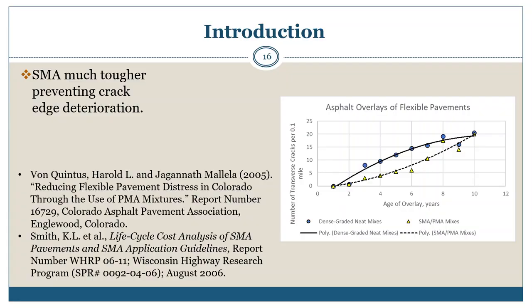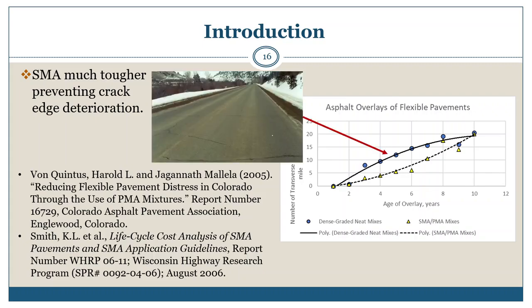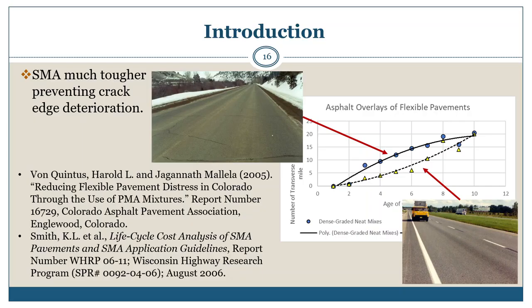The observations on crack deterioration were taken from a study in both Colorado and Wisconsin, as well as in other agencies by the presenter. The transverse cracks exhibited in conventional dense graded mixes, as shown by the photograph, exhibit more severe crack deterioration along the edges of the transverse cracks, while in the SMA mixtures, as shown by the photograph in the lower right, the transverse cracks remain basically hairline without significant crack deterioration. The reports documented for these two studies are listed on this slide.